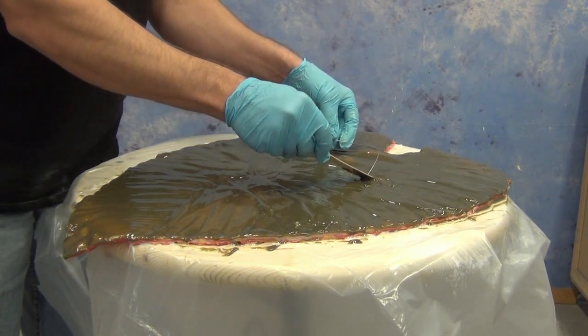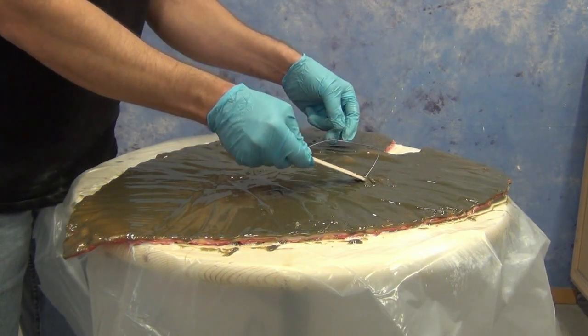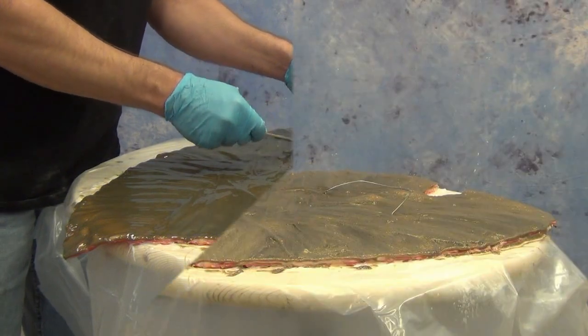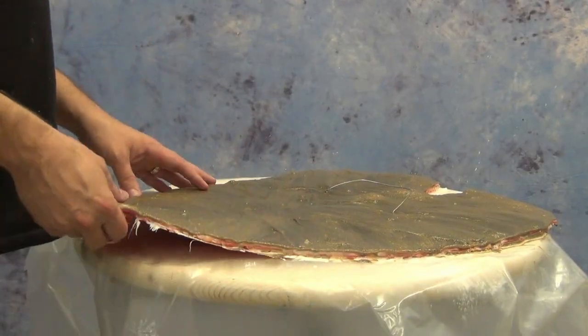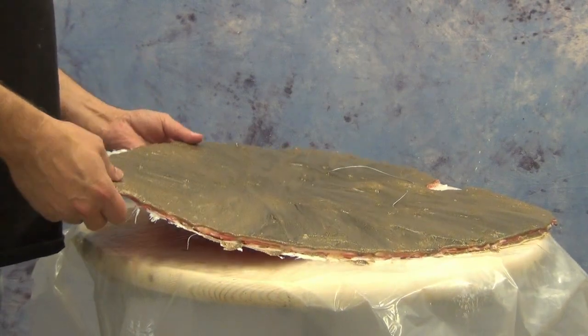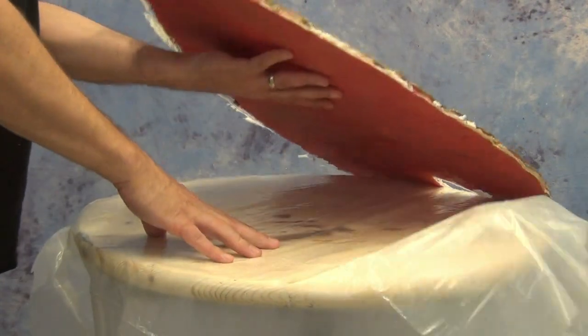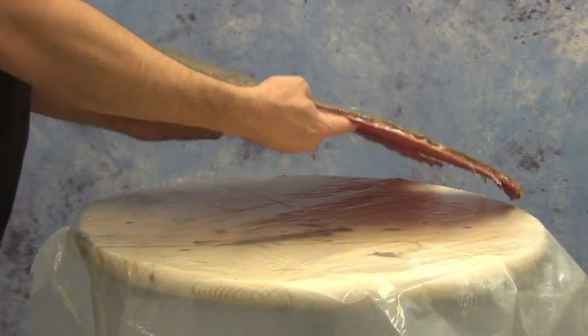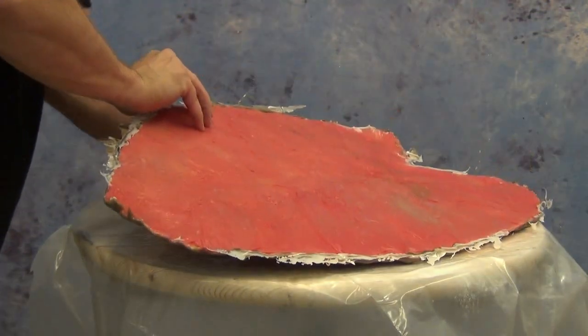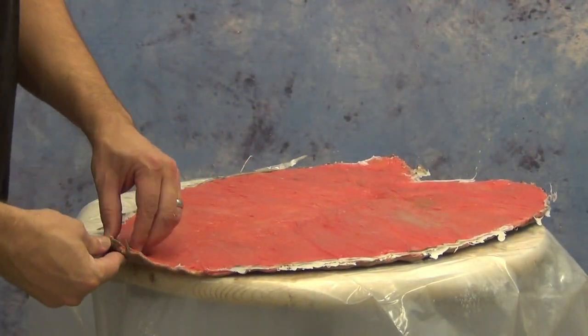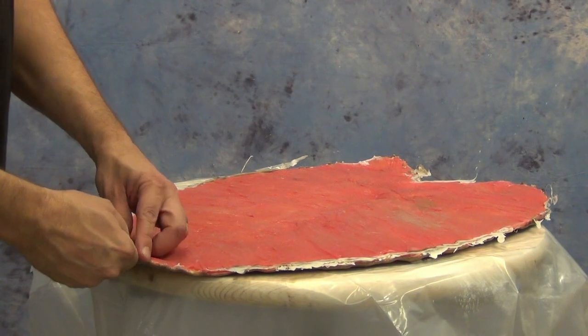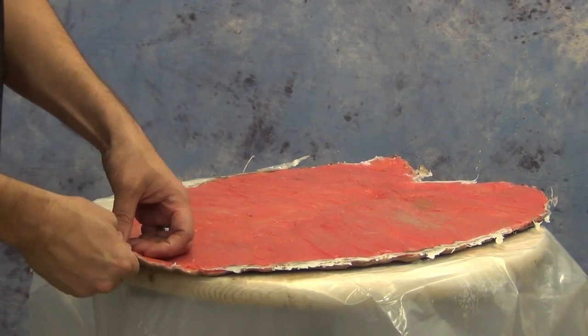Now, as I mentioned before, the BR-75D has a working time of 5 to 7 minutes and then a demold time of about 2 to 3 hours. And this particular piece took more closer to the 3 hour end of the spectrum because of the thin cross section. You'll find that thicker cross section pieces take a shorter amount of time to demold because they build up more heat, whereas a thinner cross section part like this will be a little bit longer demold.